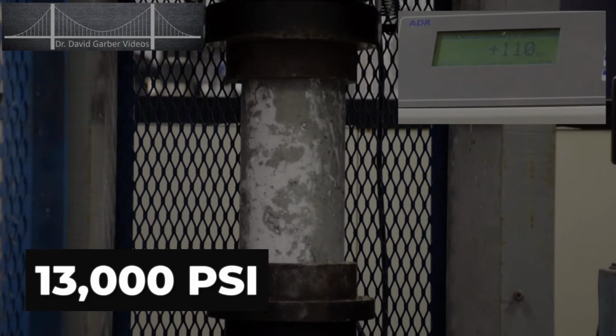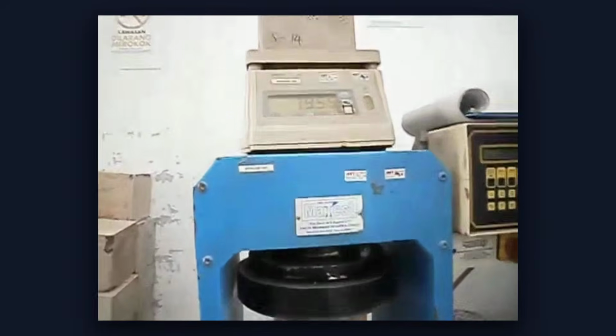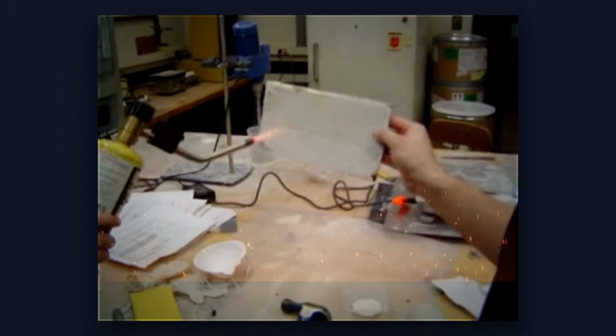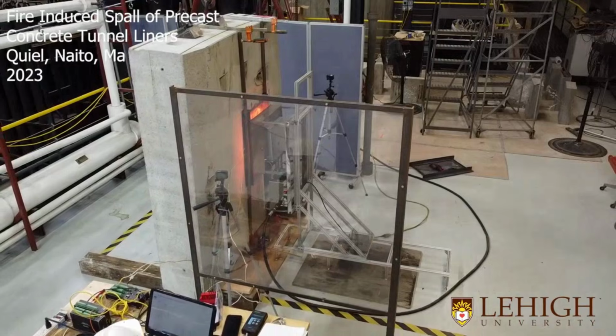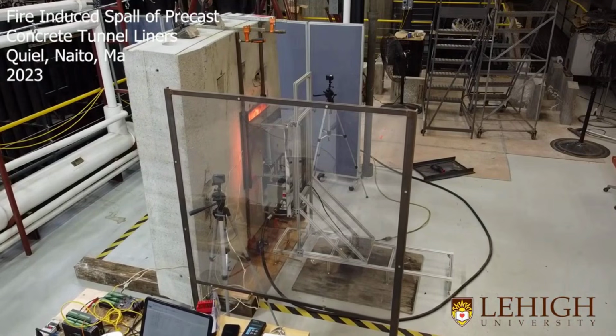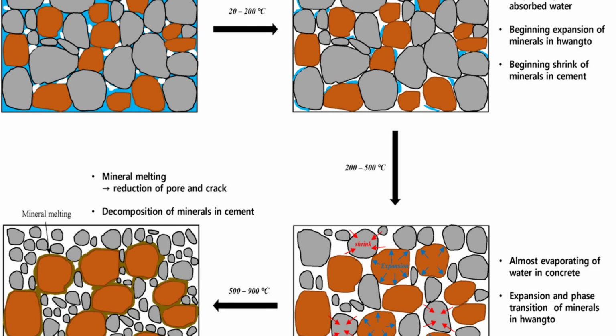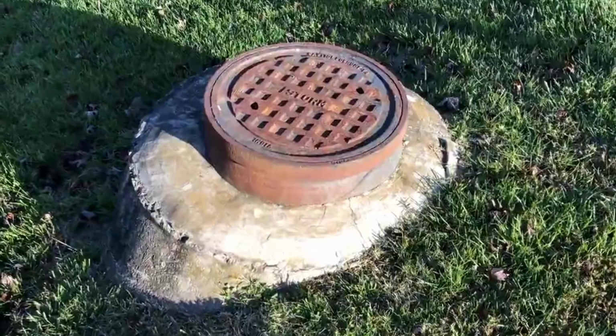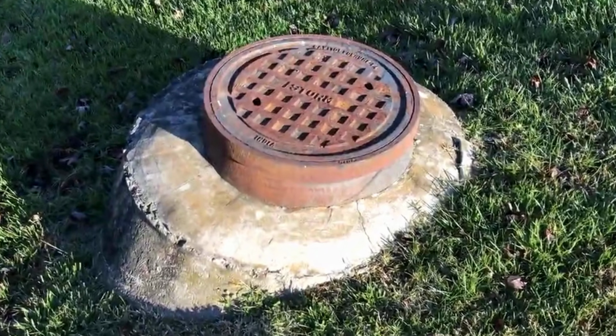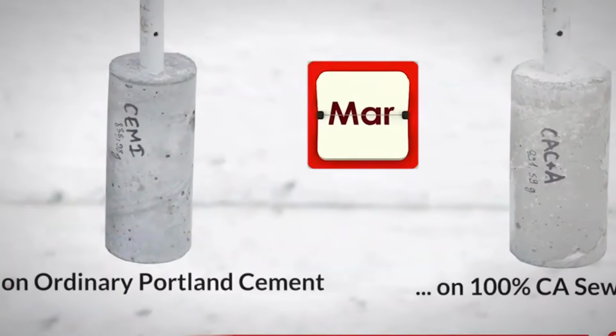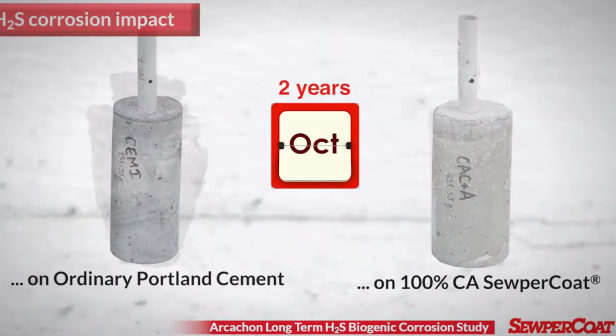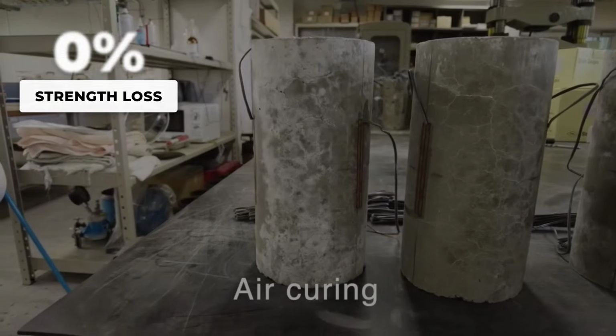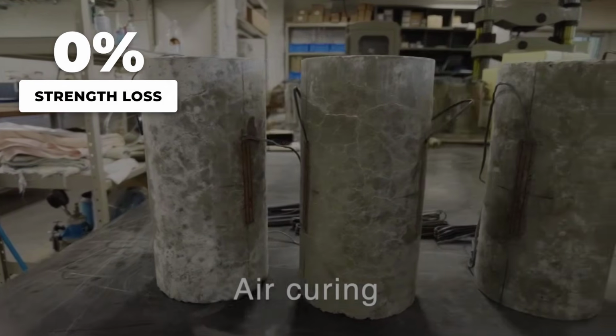Compressive strength ranges from 6,000 to over 13,000 pounds per square inch. Standard Portland cement concrete runs 3,000 to 5,000 pounds per square inch. Fire resistance holds above 2,000 degrees Fahrenheit without spalling. Portland cement concrete explodes at that temperature as trapped moisture flashes to steam. Sulfuric acid, the chemical that eats through conventional concrete in sewer pipes and industrial floors, causes barely 6% strength loss in geopolymer after 28 days.